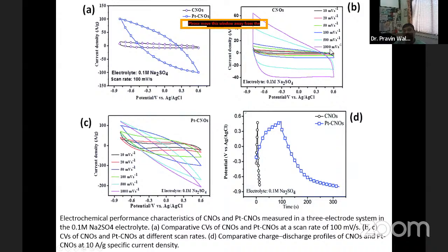It means increasing this particular scan rate value, your storage capacity is increasing drastically. And in case of platinum, you can see there is systematic increase in this particular area under the curve also, with respect to similar trend. But the only thing is you can find out there is a shift of these values towards either positive or negative side, depending on which area or range of potential you are measuring.